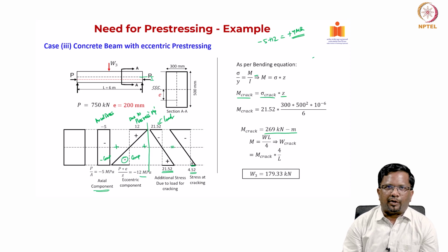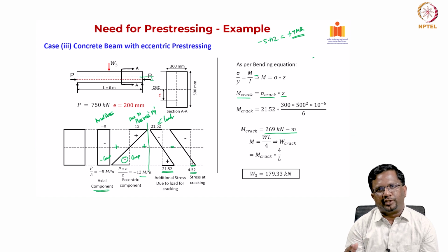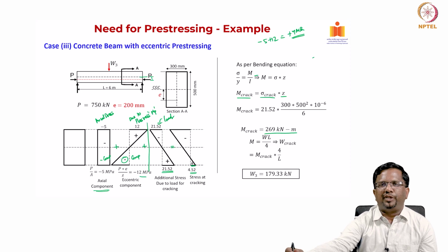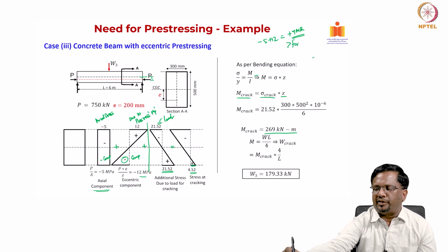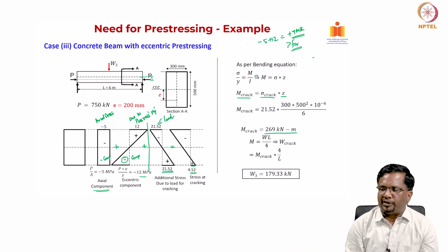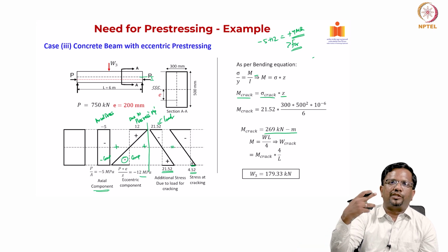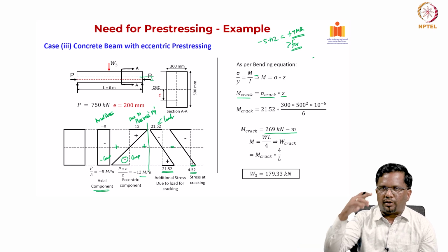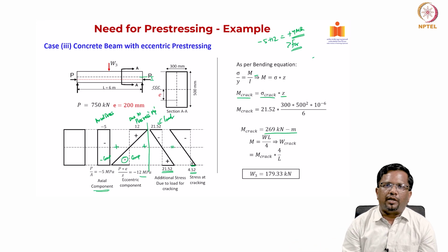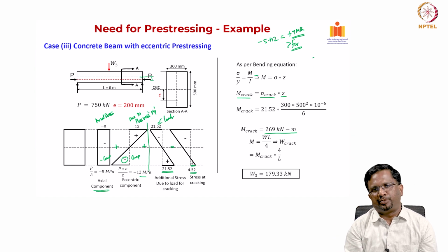In this case, purposefully we have chosen numbers in such a way to illustrate that sometimes if you apply too much pre-stress, you will have a problem. Why is it a problem? If no external loads are acting, only due to pre-stress, now the top is getting into plus 7 megapascal, which is greater than your FCR. That means, if you put too much pre-stress, you can also have cracking at locations where you do not want. So, the top fiber can get into tension and it can lead to crack. Purposefully we have chosen a slightly higher number to illustrate this point, but typically we do not do that. Stress limits are kept so that you do not apply too much pre-stress also, right.